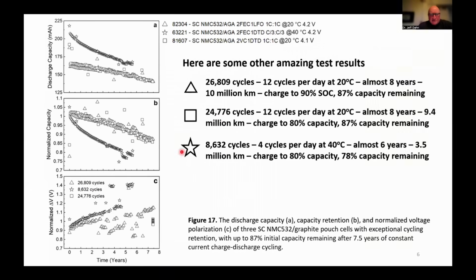And then the star data is worse, and that's because it's running at 40 degrees C, and it's doing 4 charge-discharge cycles per day. Almost 6 years of testing. It would have driven a car 3.5 million kilometers, and it's being charged to 80% every time, and it has almost 80% remaining. So 40 degrees C continuously is not found in Canada anywhere. Even 20 degrees C is higher than the average temperature in most places of Canada. So you could expect incredibly long lifetimes in Canadian conditions.